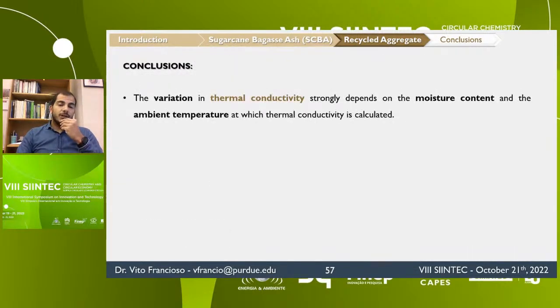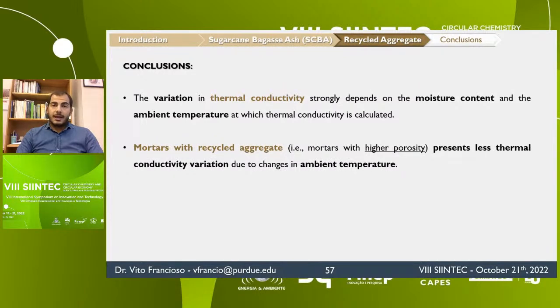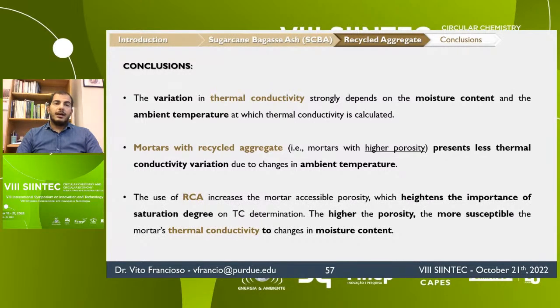So based on the results of this study, we can conclude that the variation in thermal conductivity strongly depends on the moisture content and the ambient temperature at which the thermal conductivity is calculated. Also, mortar with recycled aggregate, and therefore higher porosity, presents less thermal conductivity variation to changes in ambient temperature. And finally, the use of recycled concrete aggregate increases the mortar's accessible porosity, which heightens the importance of the saturation degree on the thermal conductivity determination. The higher the porosity, the more susceptible the mortar's thermal conductivity is to changes in moisture content.